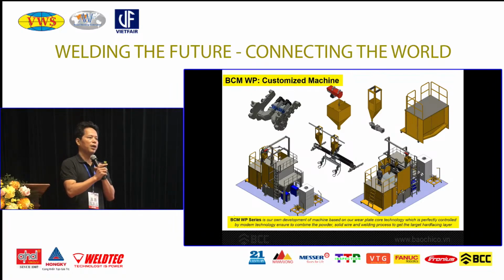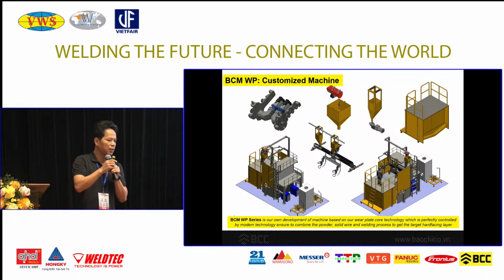And also the specification of the overlay welding, the hard facing layer, needs to be controlled. How much alloying we put in, how much chromium, how much niobium. There are many different kinds of alloy we put into the powder to make sure that it can resist the wear factor. For example, if we come to mining, the normal temperature, we just have some basic carbide